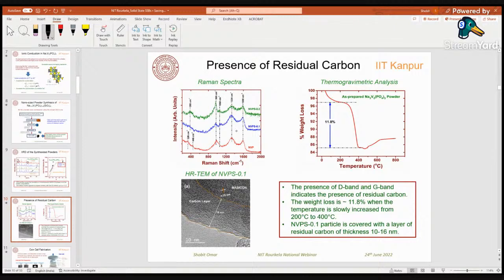If you look at the Raman spectra that we have taken over these silicon-doped compositions, we can see that there are two important peaks, the D and G bands, right? This one, and of course this one. These two show that there is some residual carbon present inside the material. And when we did the TGA, we found an 11.8% weight loss, which is mainly associated with the residual carbon. And when we looked at the high resolution TEM, we observed a coating of around 10 to 15 nanometers over the NASICON particles of NVPS. Now this coating will help to give electrical conductivity inside this material. So it will act as a current collector.